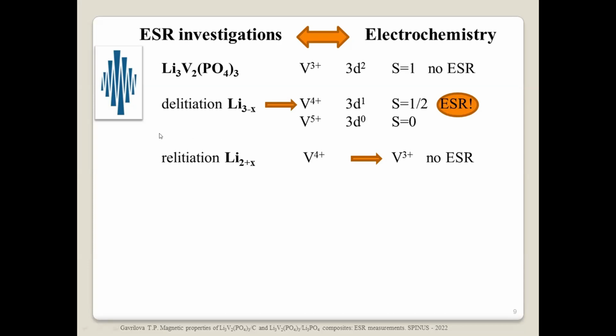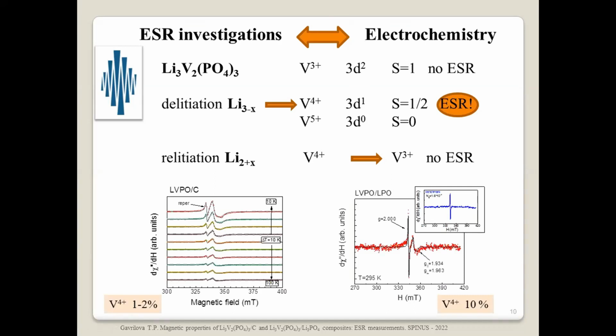During the discharge of the electrochemical cell, during the relithiation process, we can see the opposite process, as vanadium ions change their valence states from 4+ to 3+. This is the theory. What can we really see? For the as-prepared compound, unfortunately, we have already observed an ESR signal. We suggest that the signal was from vanadium 4+, which was in the as-prepared sample because of non-stoichiometry.